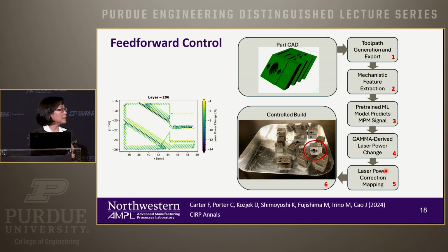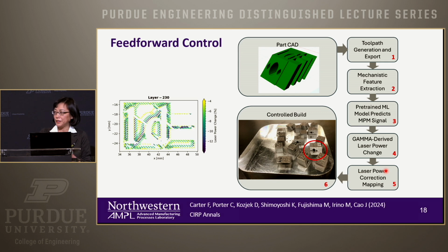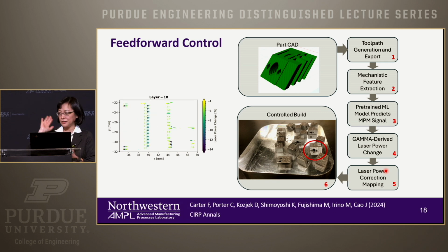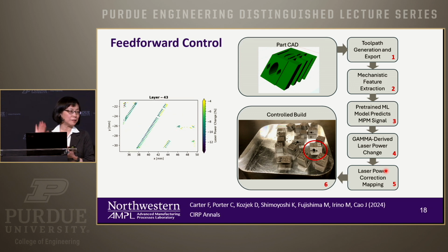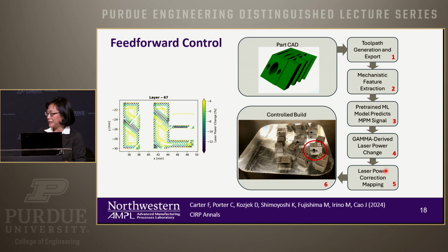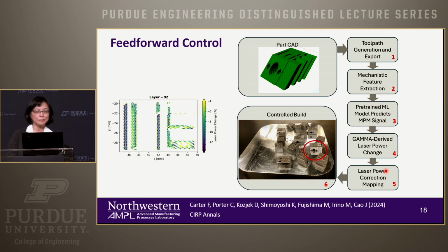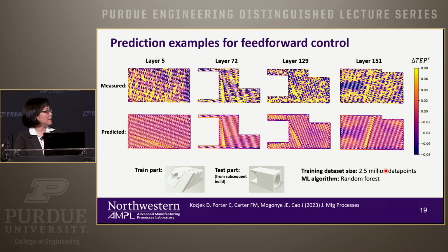And one thing, as you know, is that qualification and certification is pretty hard for AM. We hope with this one, because it's an open loop control, and we know the machine, we know what laser power we are giving, it gives a little bit easier time for the part to be qualified, right? So the key thing is, first, we need to be able to predict what's going to happen, in terms of the high temperatures where potentially you're going to get those peaks. So this is measured with the photodiode system, and here is the predicted one using the mechanistic feature that I mentioned to you earlier, and that I'm going to show in detail later.